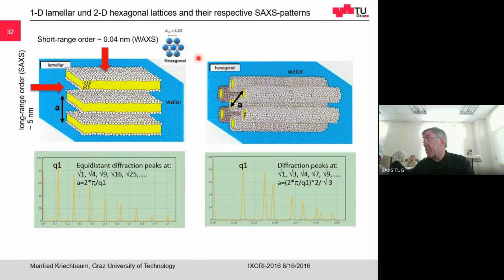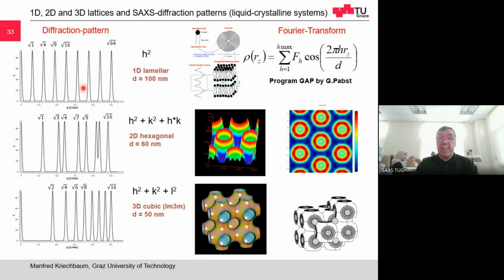You can also do simultaneously wide-angle scattering. With wide angle, you're probing the shorter distances, so you get information of the ordering of the lipid, of the lateral ordering of the lipids. This is a sample of a hexagonal structure. You get, of course, a different diffraction pattern. From the diffraction pattern, you can easily determine the morphology: lamellar, hexagonal, or cubic. So here again, lamellar, hexagonal, cubic structure.